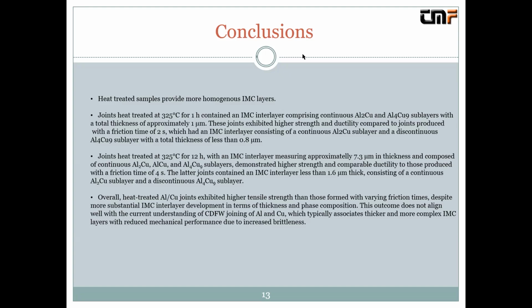So joints heat treated at 325 degrees Celsius for 1 hour contain an intermetallic layer with continuous Al2Cu and Al4Cu9 sublayers with a total thickness of approximately 1 micrometer. Those joints exhibited higher strength and ductility compared to joints produced with a friction time of 2 seconds. So intermetallic layers consisting of a continuous Al2Cu sublayer and a discontinuous Al4Cu9 sublayer with a total thickness of 0.8 micrometer show different mechanical properties.